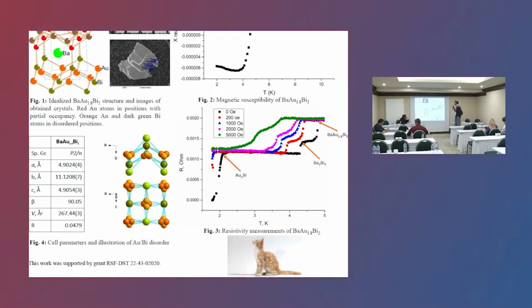For example, the barium bismuth superconductor can be achieved only at high pressures like 4 gigapascals, and gold 2 bismuth can be formed only during low temperature synthesis below 300 Celsius. In the future, we want to measure the resistivity more carefully using indium contacts exclusively to avoid any degradation. It will be interesting to measure more transport data like the Hall effect, and probably use some DFT calculations, because the conductive layers in this structure are bismuth-gold layers, and bismuth and gold both have huge spin-orbit coupling effects, and it will be interesting to look into the interplay of these effects and superconductor properties. I think that's all.